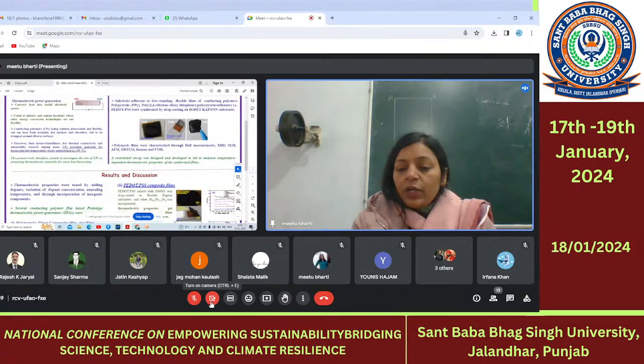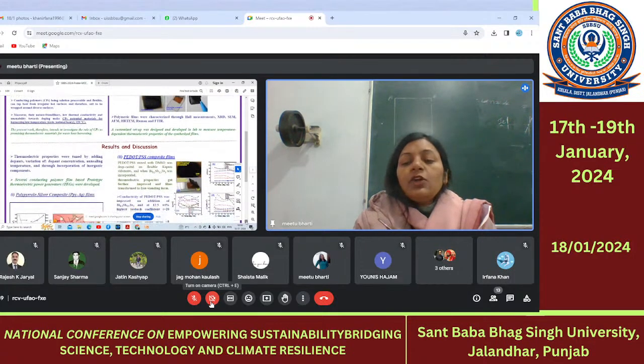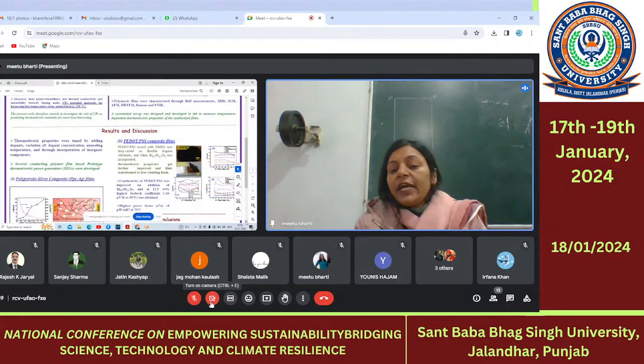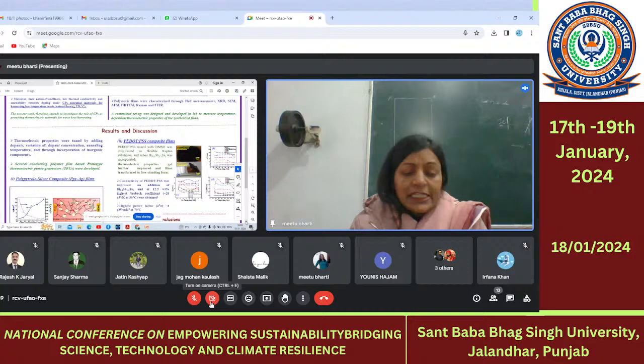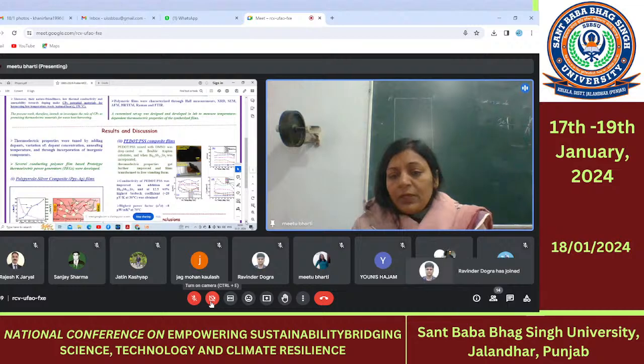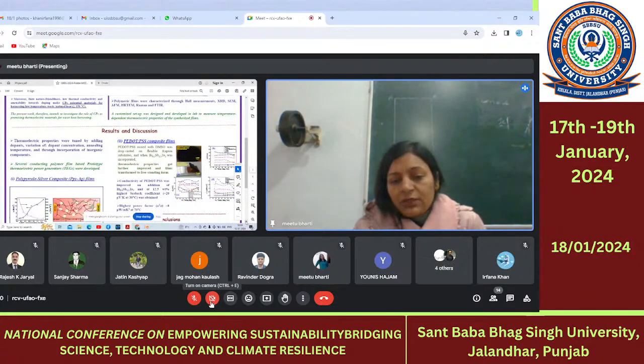Now, in case of PEDOT:PSS composite film, we mix the bismuth antimony telluride, which was synthesized in our lab, with the PEDOT:PSS solution and simply drop cast it. From the figure, you can easily see that the first figure is substrate adherent on Kapton, and the second figure is just peeled off due to the addition of bismuth antimony telluride. Such freestanding, or self-supporting film, can be used to fabricate wearable generators, which can be used to trap body heat or the heat of irregular surfaces.